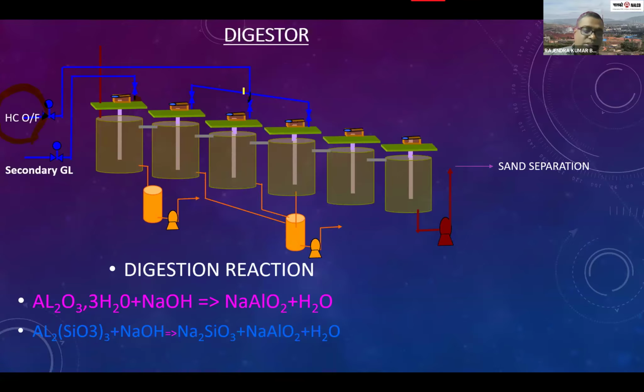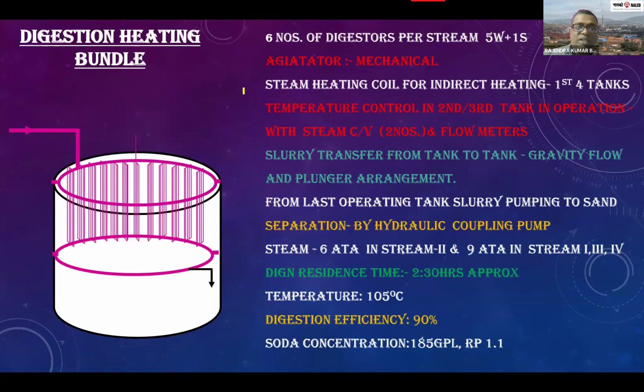These are the heating bundles. These are the agitators, and these are steam bundles. We are injecting the steam through this ring, and these are heating bundles. Residence time is 2 to 3 hours approximately. Temperature, we are heating with steam, is 105 degrees centigrade. Digestion efficiency is 90%. Soda concentration is 185 GPL.